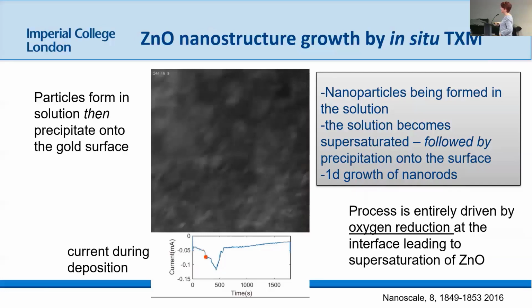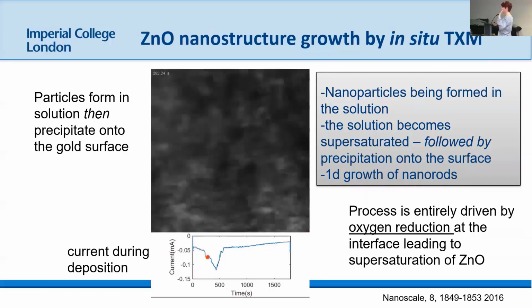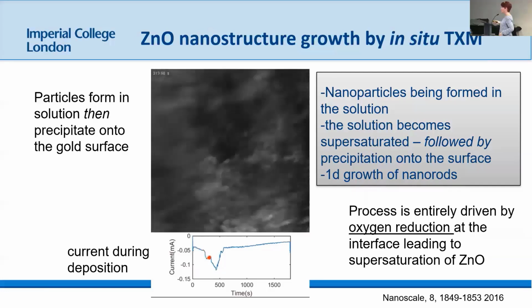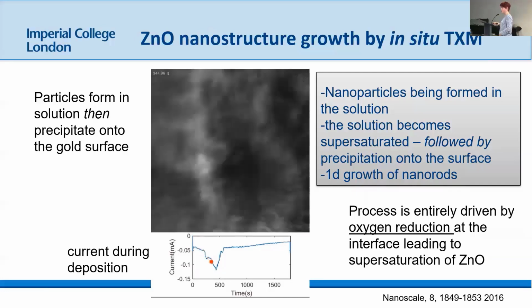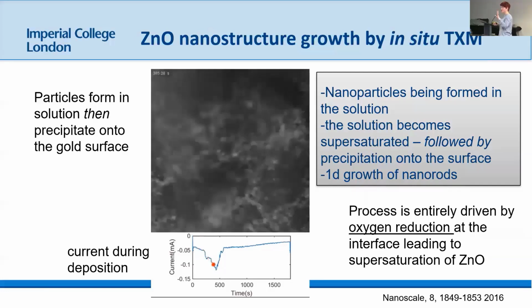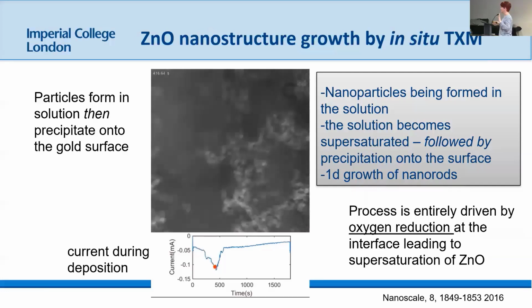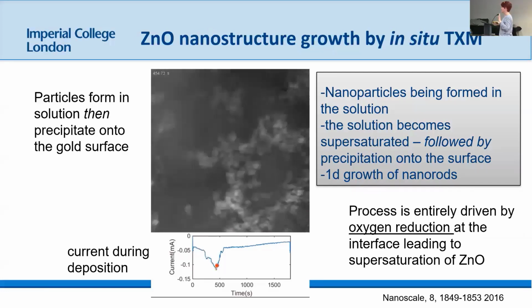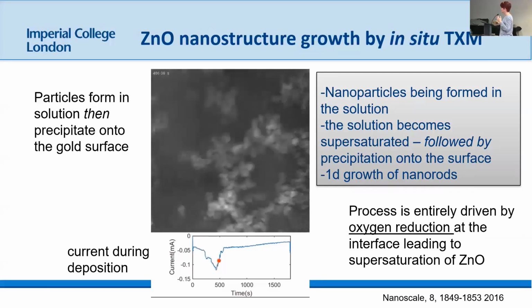contrast in the system. And remember, my electrodes are going right the way through my electrolyte. And what you're seeing there is supersaturation and nucleation in the solution of these colloidal nanoparticles. And they slowly then deposit on the surface and they'll grow as we go.